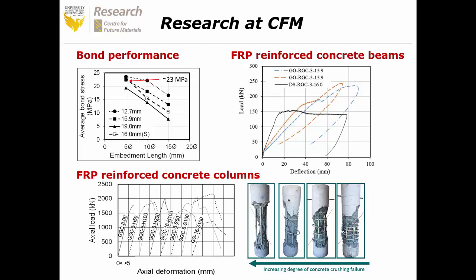This graph compares the bond strength of FRP bars to that of steel reinforcement. 23 megapascal is the bond strength of steel reinforcement. And as you can see here, FRP bars of the same diameter exhibit almost the same, or in fact slightly higher, bond strength to concrete. And why is this result important? Because this result tells us that FRP bars can bond sufficiently with concrete to provide total composite action.